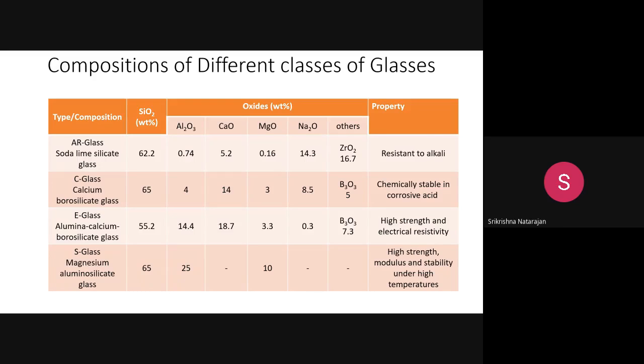And if you see the other glass, which is called the E glass, the electrical resistant glass, this is otherwise called the alumina calcium borosilicate glass. Okay, so if you see the words calcium borosilicate or soda lime, it means you can observe from here itself that these metal oxide percentages will also be higher. You can see here in the E glass, apart from the silicon dioxide, the alumina trioxide is higher, the calcium is higher, and here the B2O3, which is the borosilicate, is also used more. This borosilicate is used in both the C glass as well as the E glass.